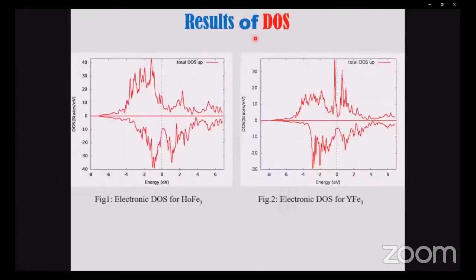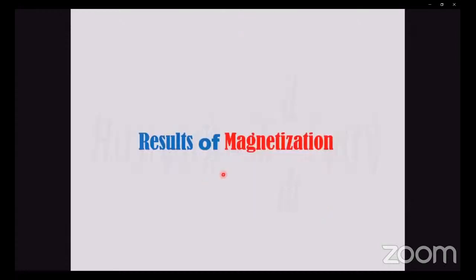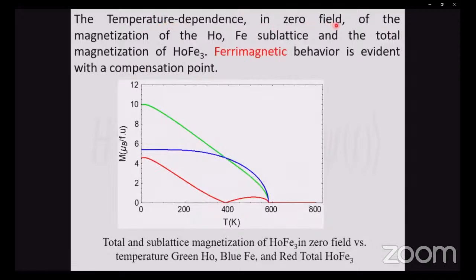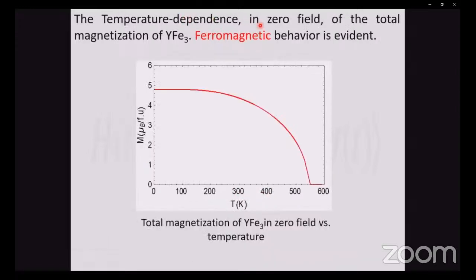The results. First, the results of density of states. Here, we calculated the electronic density of states of both holmium iron three and yttrium iron three to get the density of states at the Fermi level that we need in our calculation. The results of magnetization. The temperature dependence in zero field of the magnetization of the holmium and iron sublattices and the total magnetization of holmium iron three: ferrimagnetic behavior is evident with compensation temperature of 395 Kelvin. The temperature dependence in zero field of the total magnetization of yttrium iron three shows a ferromagnetic behavior.